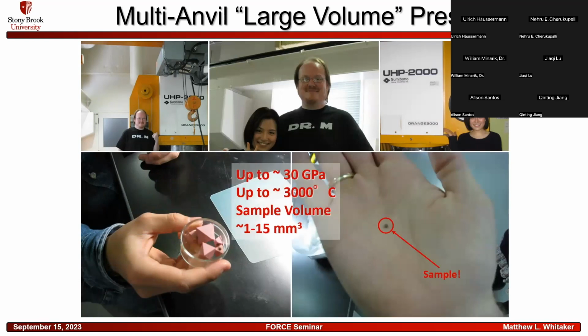Oh, okay. So here we can see some of the cell assemblies that go into the multi-anvil press. And again, we can get up to about 30 GPa and 3,000 degrees centigrade. But the sample volume, again, is very small. You can see that it shows up as just a speck in the palm of my hand there.